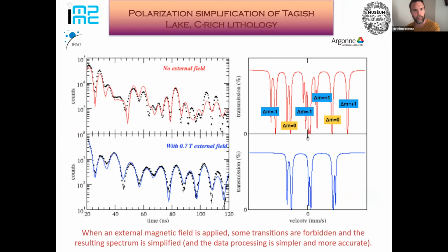Because the results were quite complicated, and this was partly due to the fact, as you will see soon, that there is a lot of magnetite and pyrrhotite in these Ryugu samples. We also used for the first time, I think, the polarization simplification on natural samples. The idea is to use an external field of 0.7 Tesla in order to quench some of the lines that you find in magnetic materials, especially on this figure for magnetite, the lines associated with delta m equal plus or minus 1. Because this produces spectra that are simpler to fit.